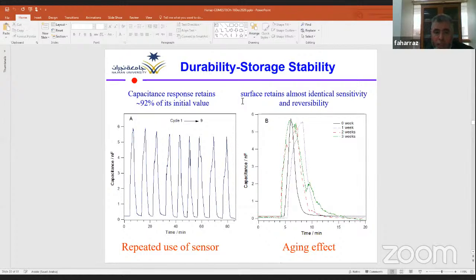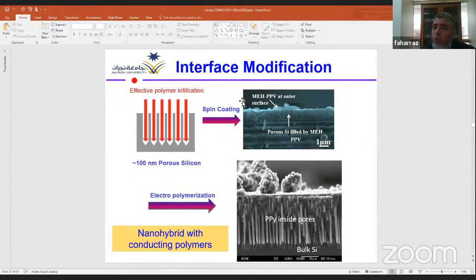Our device is stable, and we have been able to reuse the sensor for several cycles, and the capacitance response retains around 92% of its initial value. We also observed minimal aging and storage effect for our device. Now, we recently tried to make another progress in terms of sensitivity and response time via modification of the interface. Our strategy here is to make some conducting polymer infiltration inside the nanopores. We can obtain a nano hybrid of conducting polymer with the porous silicon via spin coating and/or electropolymerization.